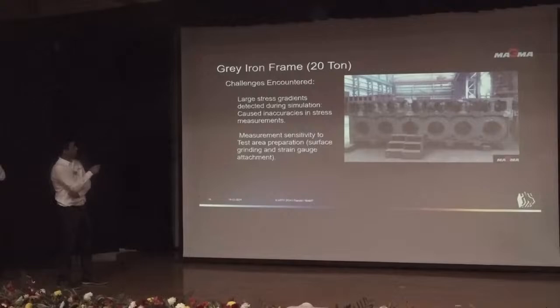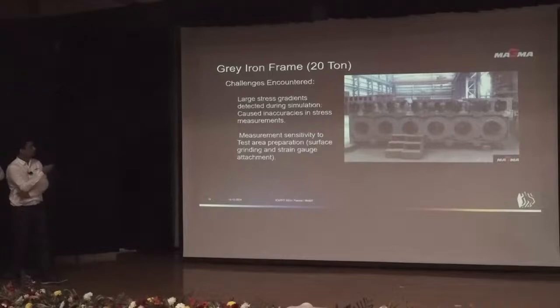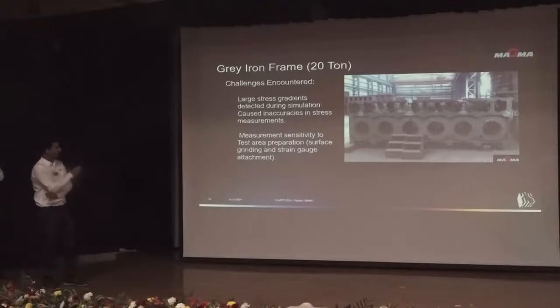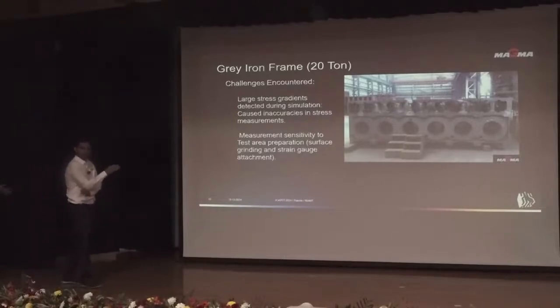So there is another case of gray iron frame. Next, what we learn about after that is that we have to locate the locations in casting where we are going to do that. So in this casting, what was the challenge? That large stress gradient was detected during simulations. So the sensitivity of the measurement tools, like we do surface grinding and we use strain gauges, and the accuracy of where we are going to put them or where we are going to measure them, needed to be evaluated before.